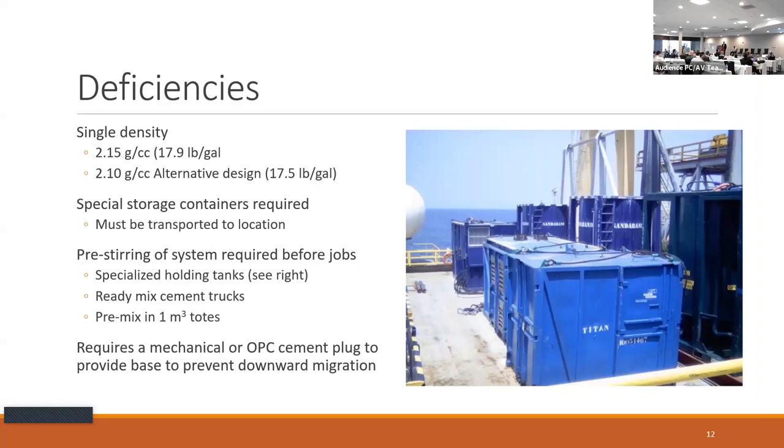As we thought about it, we've seen that we can probably put this in ready mix mixers and bring it out to location and have it shear and then just pump it down hole. So there has to be some type of pre-stirring before you go down hole. When you get the material after it sat for a long time, you can walk on it. I mean, you don't have to be Jesus to walk on this stuff. You can just walk across it and it's fine. But after you shear it, and they've got some videos online that you can watch, I don't have one with me now, but you can shear this and fluidize it. Once you fluidize it, you can pump it with regular cementing pumping equipment.